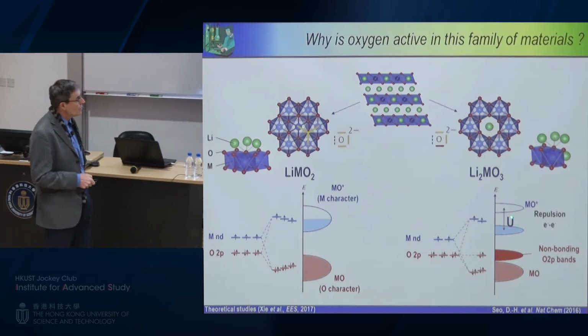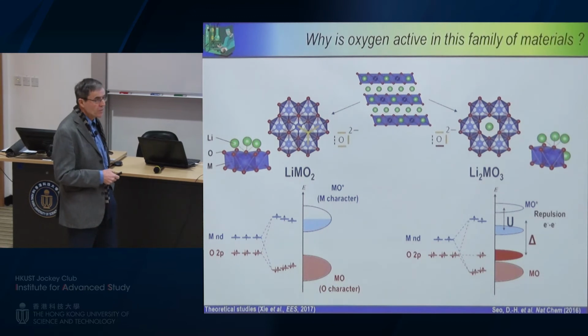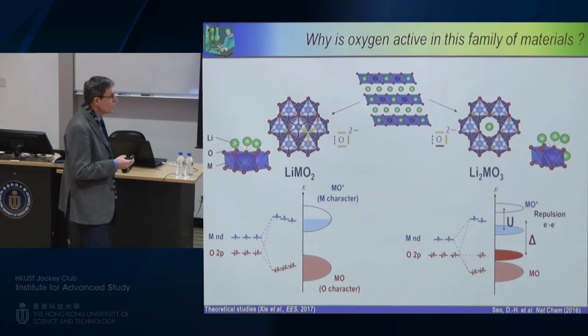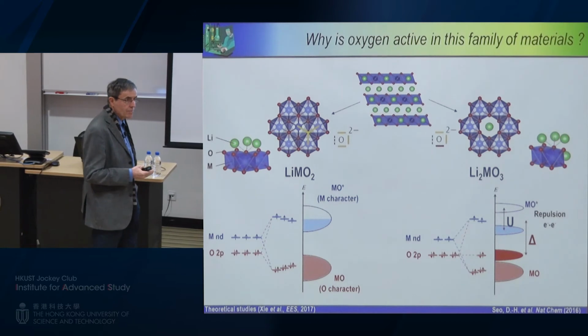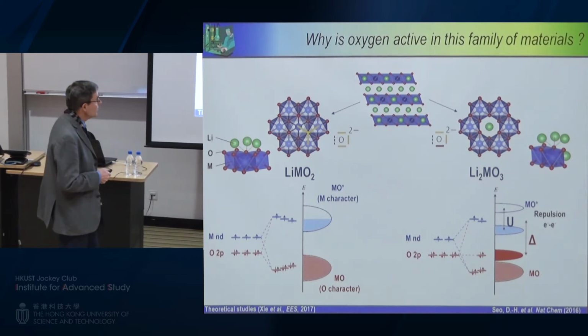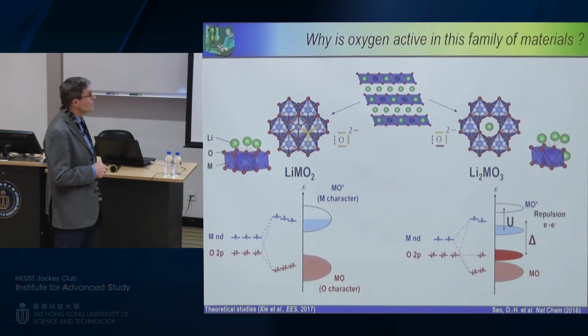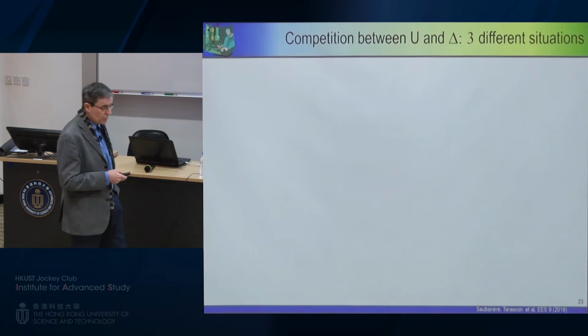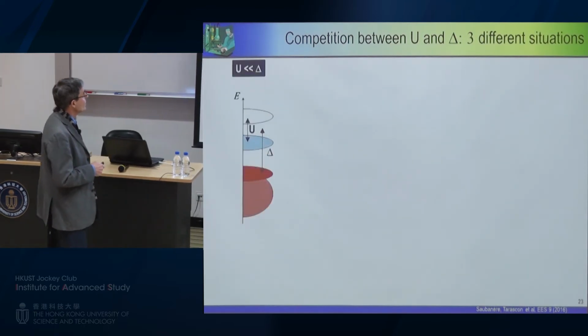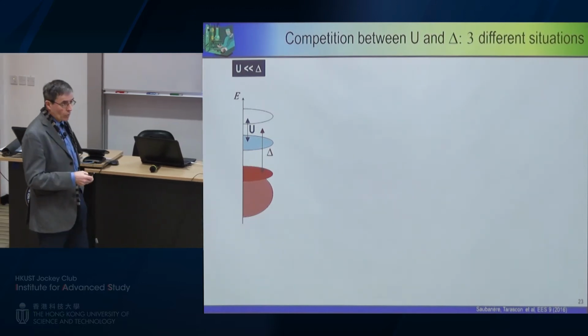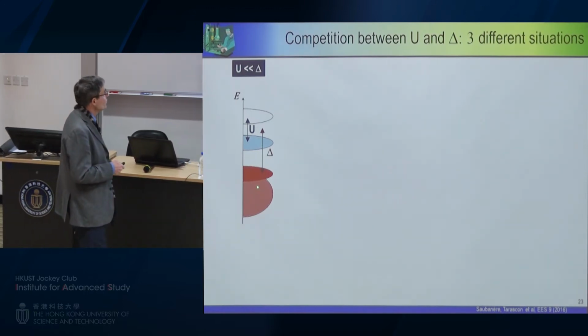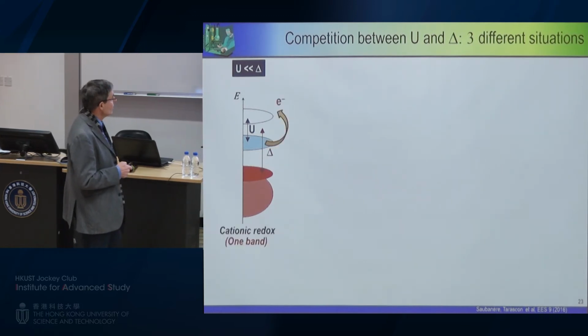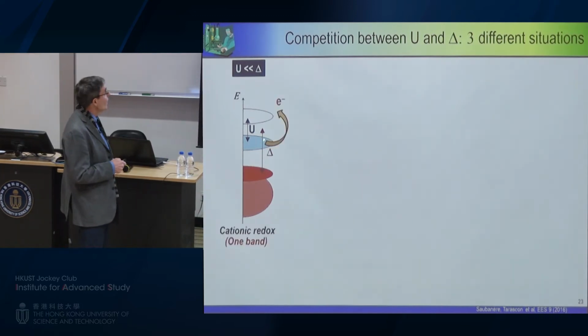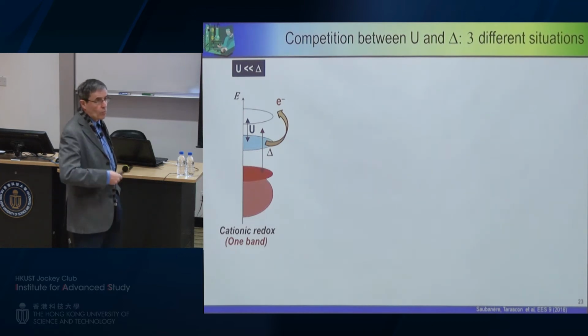And this term, U, now is going to compete with the charge transfer. And this is going to give me several situations that I have to consider. And indeed, if I look at this case, I can have three different situations to explain all my electrochemistry. First, if I am in the case of classical Mott-Hubbard, where U is quite smaller than delta, I have this configuration here. This is a classical case of cationic redox, where